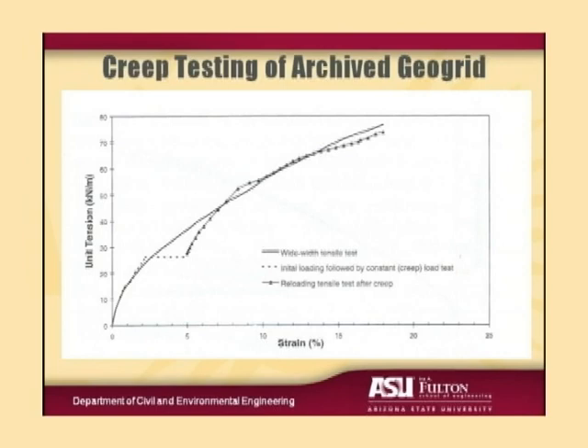We did a wide width tensile test, an immediate short-term loading test to get the solid line, and then we would do creep tests. I think the longest creep test was up to 6 months. We had a project schedule to meet. But the important finding was that when we reloaded it after creep, much like soils, we had an initial stiffening of the response, but eventually it essentially came back to the static stress-strain curve, the immediate loading stress-strain curve. And you'll notice here then that we would get out to strains on the order of 15 to 20% without rupture of the geogrid.